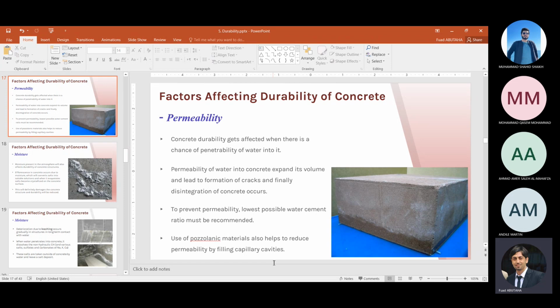So how does this happen? Because the particle size of the cement is different from the particle size of this material. If we take silica fume as an example, the particle size of the silica fume is 100 times smaller than the particle size of the cement. So these small particles fill the voids between the cement particles. It will make the concrete more dense and compacted, and will contribute to preventing and avoiding the permeability of the concrete.